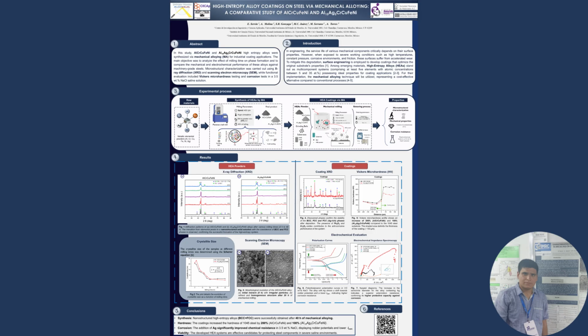In conclusion, nanostructured high-entropy alloys were successfully synthesized after 40 hours of milling. Both coatings substantially enhanced the baseline hardness of industrial machinery steel. Furthermore, the addition of silver proved to be a critical factor in improving chemical stability against saline environments. Therefore, these developed high-entropy alloy systems represent highly effective and viable candidates for protecting structural steel components in severe marine or industrial conditions.